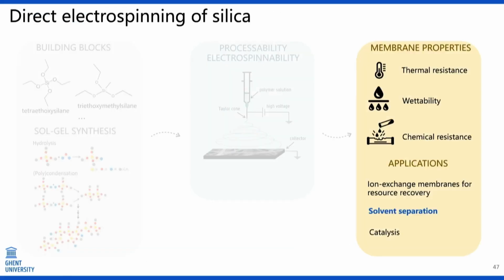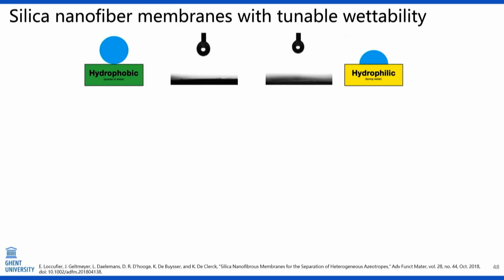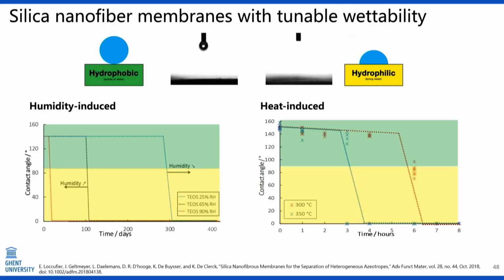Then in addition to ion exchange membranes, we also use these membranes for solvent separation. And here we took advantage of the tuning of hydrophilic, hydrophobic properties. When you produce these silica membranes, they're hydrophobic. But you can make them hydrophilic by giving them a heat treatment, or if you store them under humidity, in the end they will become hydrophilic. Won't go into much detail, it's because of network reformations and so on.